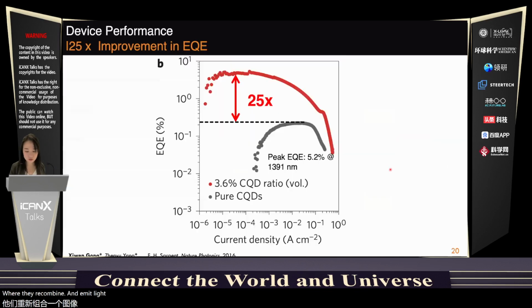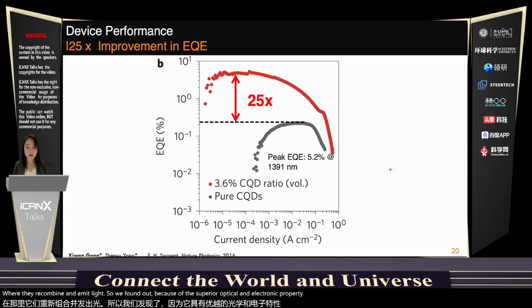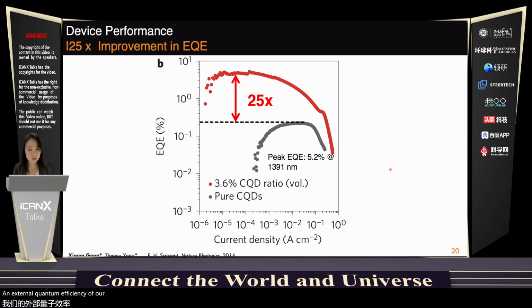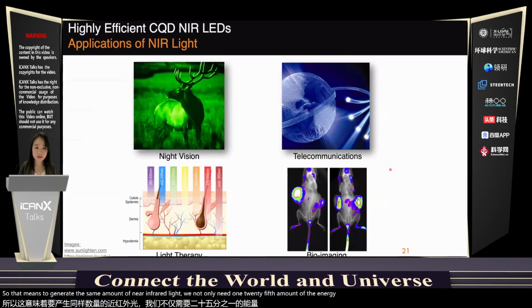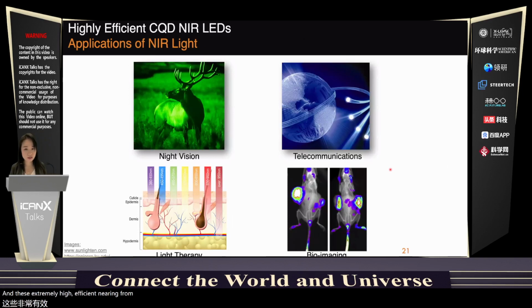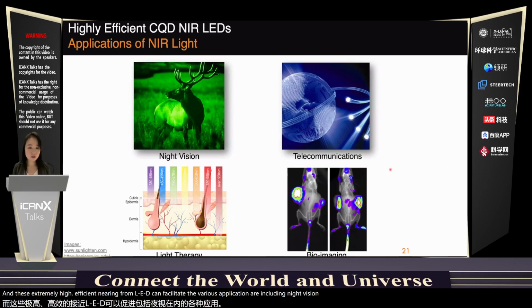So we found that because of the superior optical and electronic properties, the external quantum efficiency of our quantum dot LED reached a record high of 5.2%. And that is actually a 25 times improvement compared to quantum dots with just ligands. That means to generate the same amount of near-infrared light, we need only 1/25th of the energy. And these extremely efficient near-infrared LEDs can facilitate various applications, including night vision, light therapy, bioimaging, and beyond.